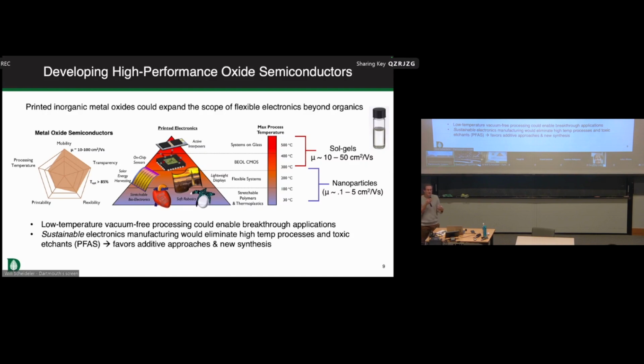But if we think about flexible and printed electronics, the challenges when it comes to metal oxides are, can we manufacture them at lower temperatures? If you look at some of the applications that these materials have in, for example, energy technologies like solar cells, in flat panel displays, in active interposers, these get more interesting the lower in temperature that we go. So if we can manufacture our materials at temperatures that are compatible with plastics, this is typically a range of 250 degrees or lower, then it means that we can have devices that are flexible or stretchable, that have all these other mechanical functionalities that we couldn't otherwise.